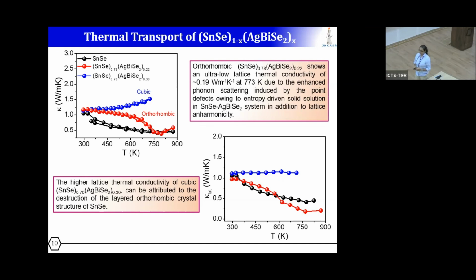But then how can thermal conductivity increase? The electrical thermal conductivity can increase, sir, because according to the Wiedemann-Franz law, sigma is proportional to kappa electrical. But if you look at the lattice thermal conductivity, the lattice part is not actually increasing, it's almost constant. So we cannot say from the total thermal conductivity, but if you look at the lattice contribution, it is almost constant.